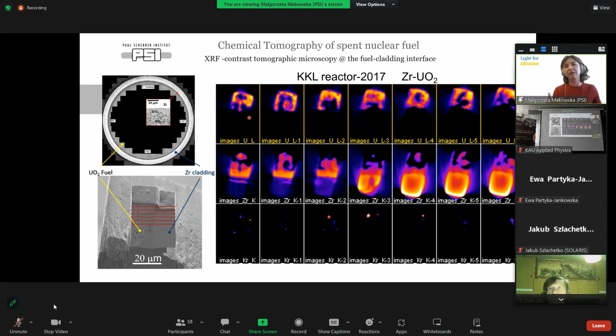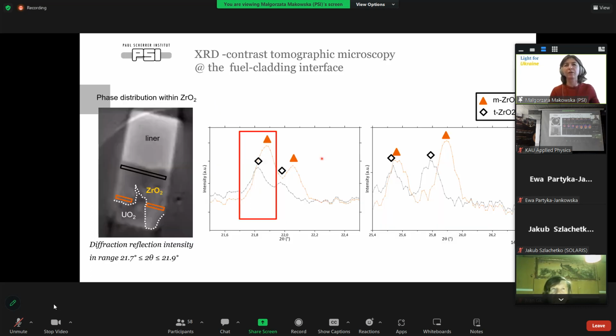And here we can nicely see how zirconium is intercalating into the uranium oxide. And in fact, this phase that we see here, which we could then recognize from diffraction contrast, was zirconium oxide. So we see the zirconium oxide growing into the fuel. So I will move forward.